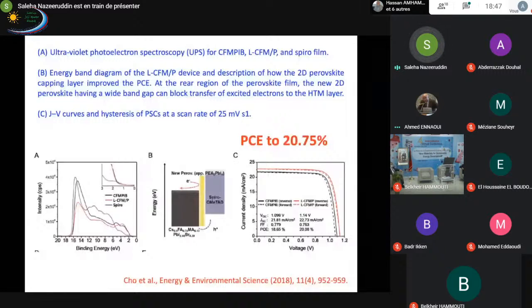So how do we know that this is happening? Let's take the PV data. On the left side, if you look at the reference sample, the VOC is 1.09 volts. After depositing this two-dimensional perovskite, the VOC has increased from 1.09 to 1.14. So the efficiency goes from 18.65 to 20.08, and the final optimized efficiency is 20.75. What this shows you is that the creation of this interface layer is reducing the recombination at this interface, which is increasing your VOC.